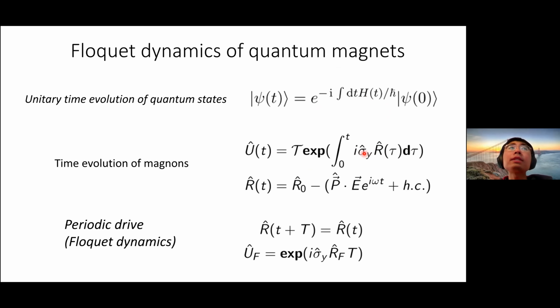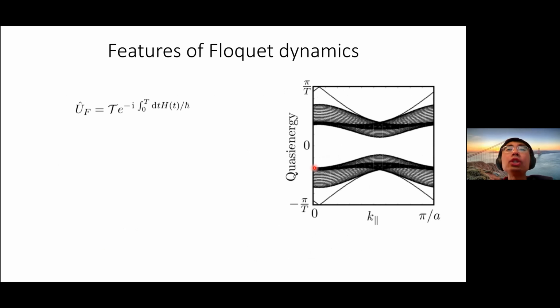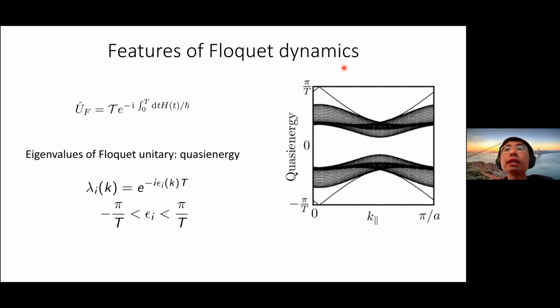So in this case, what we want to do is couple the system with light. Again, the coupling to leading order is electric polarization coupled with the electric field, and of course this will depend on the material, on how large this coupling is. We want to consider such a periodic drive, where the frequency is given by the light, and we'll ask what could happen in this case. One immediate difference in the so-called Floquet system, or periodically driven system, is that the energy is not really conserved, but rather there is something known as quasi-energy that's conserved.